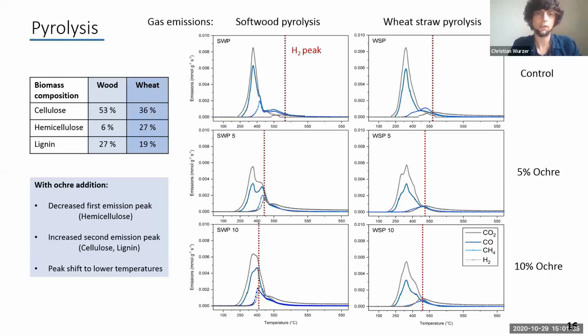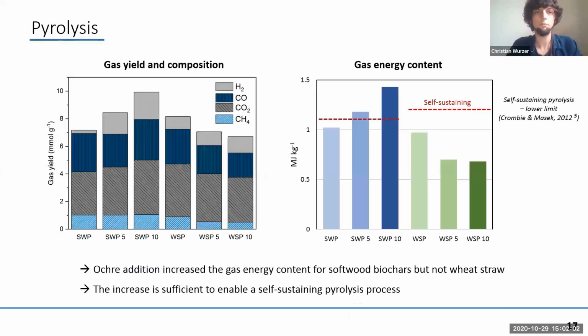But the most interesting part is the change in the hydrogen peak, indicated here in red. You can see that the presence of iron is shifting the peak from 550 degrees down to around 400 degrees for ochre-added samples in the softwood feedstock. And most importantly, it's also decreasing the size or the amount of hydrogen emissions, which we can see on the table on the left. So here you have the total gas yield and the composition.